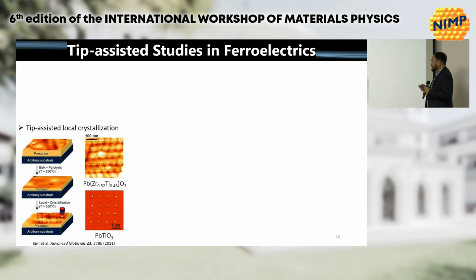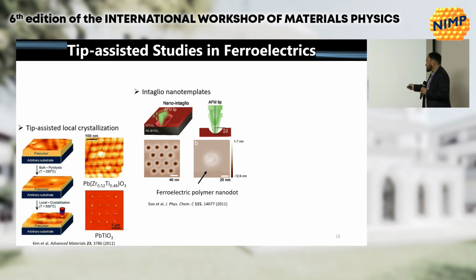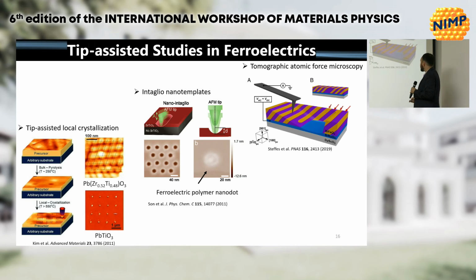Other tip-assisted studies in ferroelectrics include local tip-assisted crystallization, carving holes into a material to then create a place for a polymer nanodot to be deposited. And a great example recently from Brian Huey's group in Connecticut, where they did exactly that tomographic approach, where they removed the material and measured the domain structure as a function of depth.